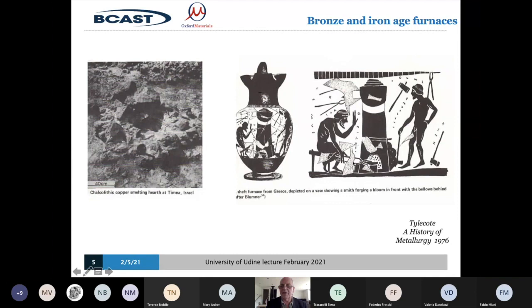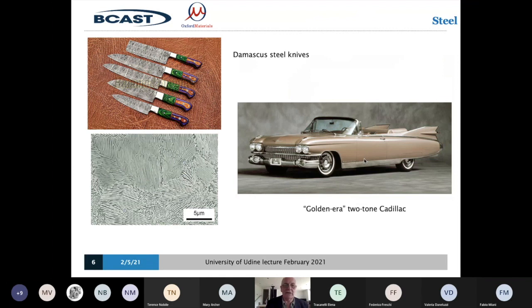You can see a blacksmith here pulling out of the fire some rather poor quality wrought iron, and he's going to hammer it to make it a little bit better. In the Industrial Revolution, we have steels. If you have 0.8% carbon, then the steels have this alternating mixture of nearly pure iron and an iron carbide called cementite, Fe3C. And this, when it's hammered, produces these beautiful pictures on knives. It's called Damascus steel. That's quite a high carbon content for a steel. It's at the upper end of carbon contents, and that's a very high strength steel.